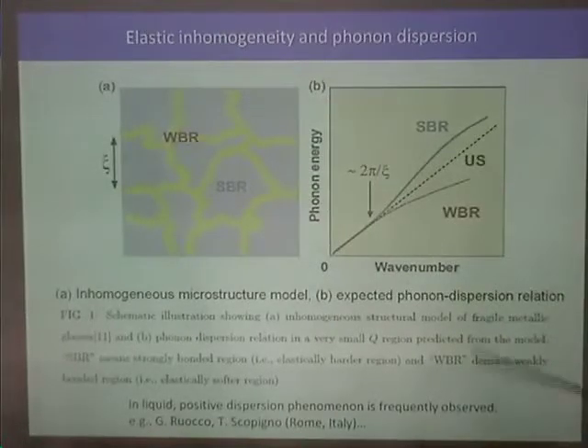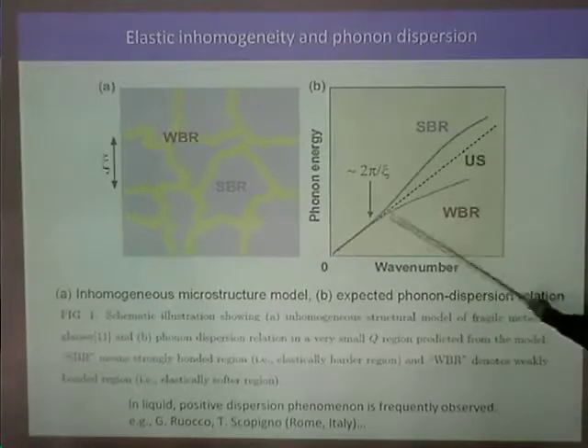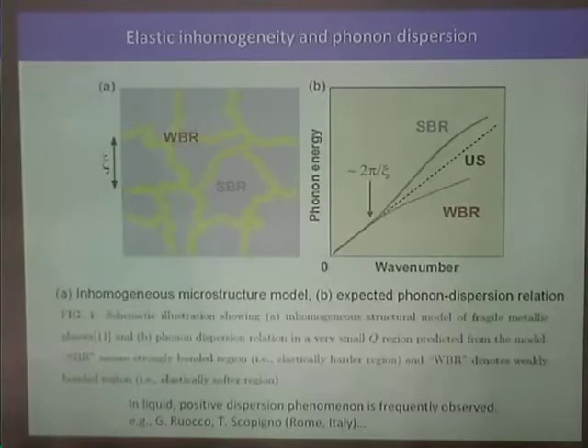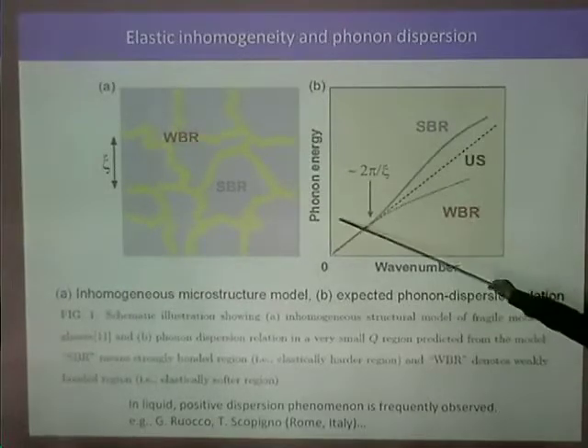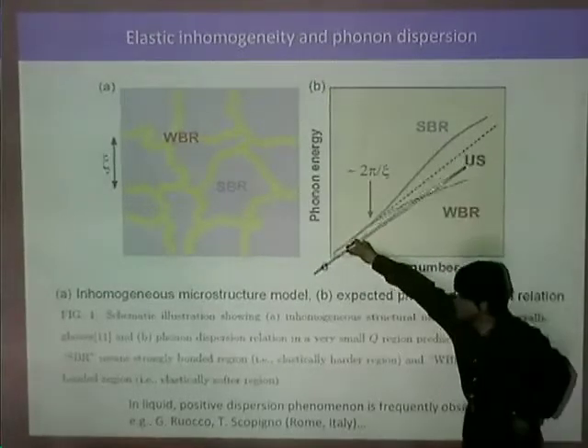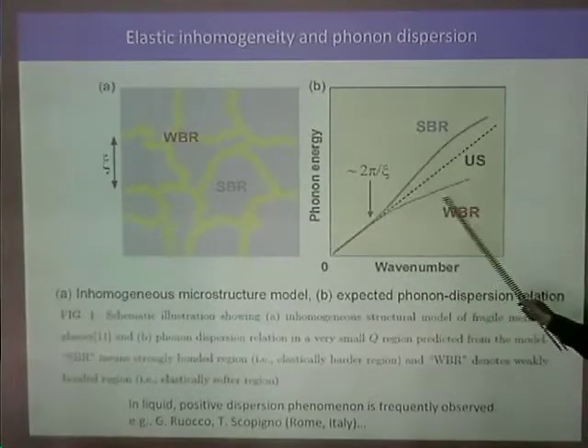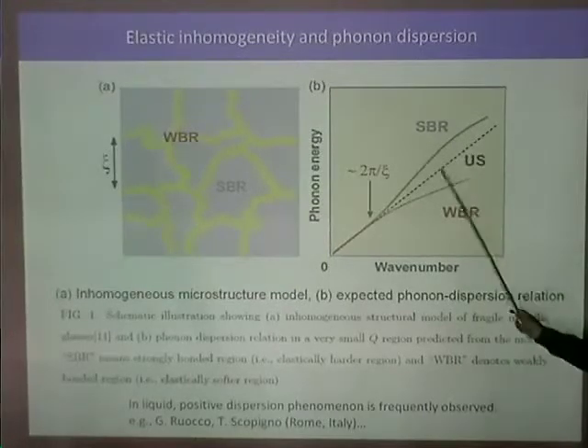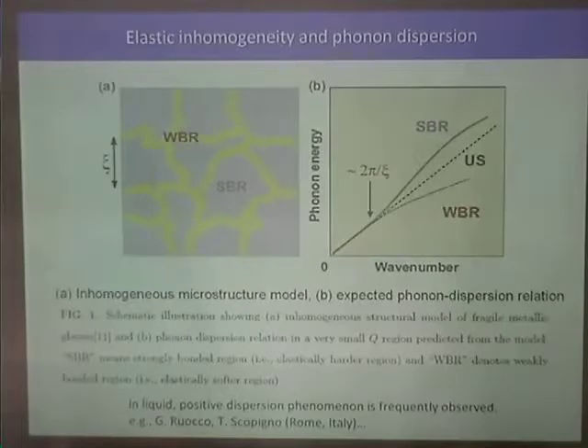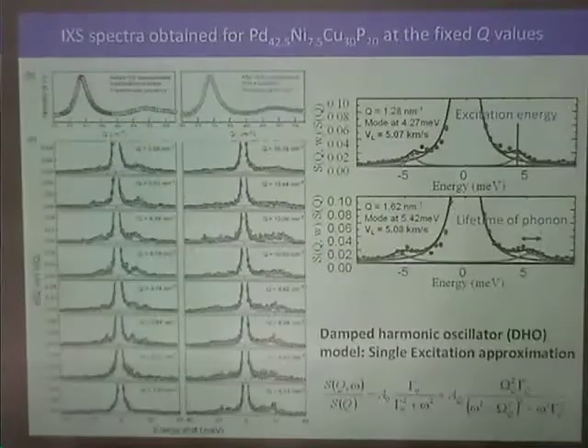So if this microstructure is realized, the phonon dispersion should be like this. This is the macroscopic average. The hard region has harder elastic constants. Therefore, for the phonon energy, this slope means the sound velocity of the phonon. Therefore, it deviates positively. So this is a positive dispersion. In liquids, positive dispersion is frequently observed, but in the case of solids, positive dispersion can't be explained theoretically, if observed.